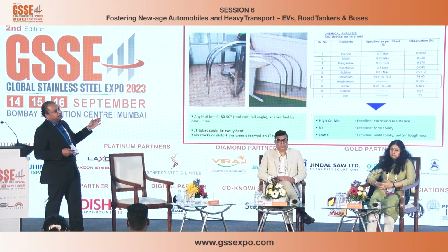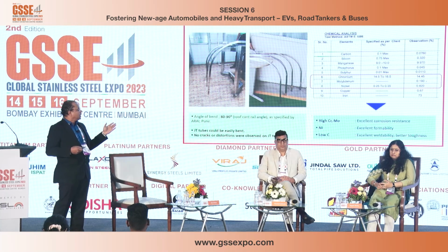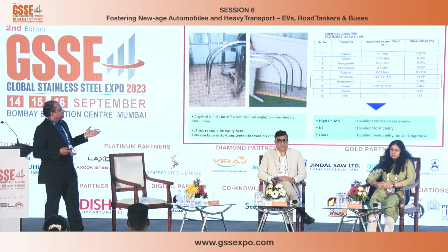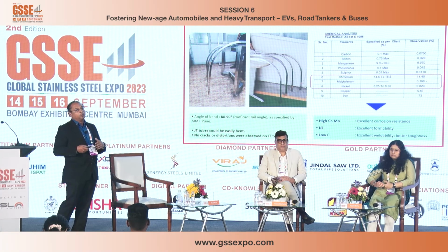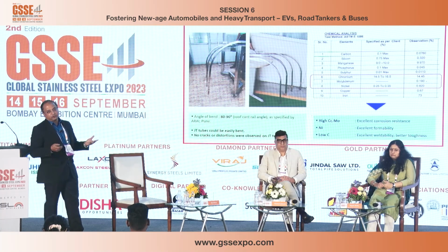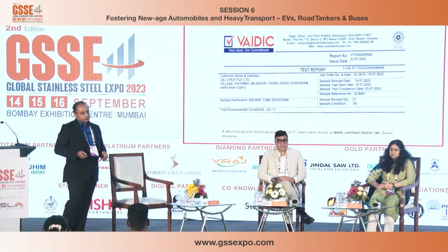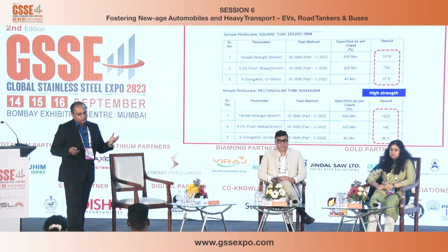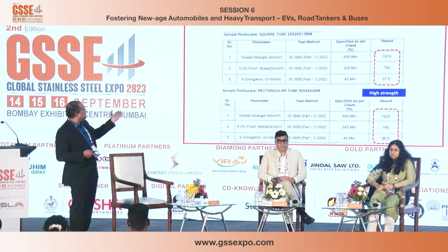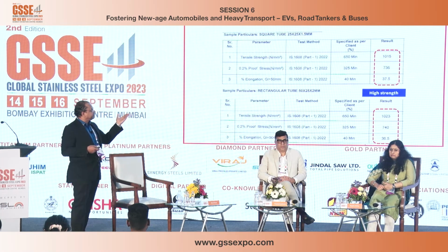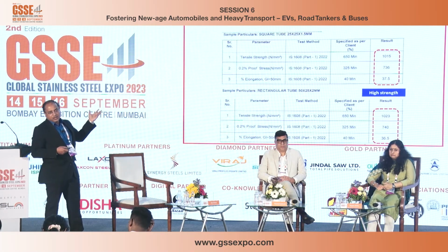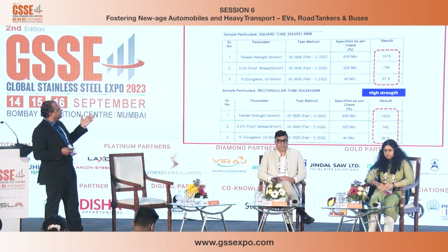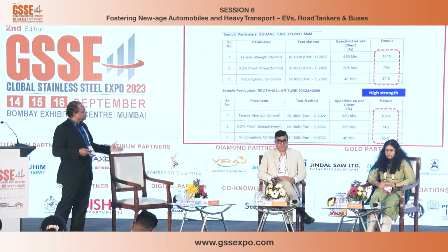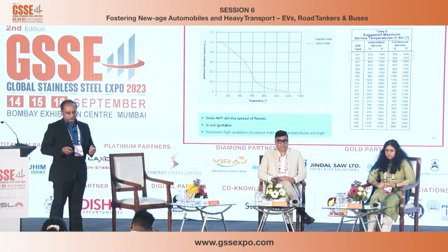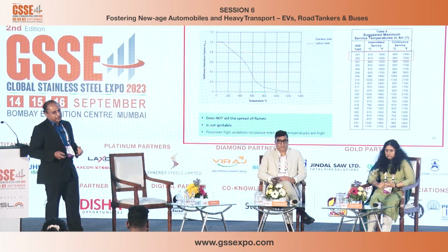And the carbon content is substantially lower. It's about 0.1%, and therefore with lower carbon, the weldability improves. In fact, the toughness also improves. So we did some tests, and as you can see, the YS is coming to about 736 megapascal for various tubular profiles. So this is 25, 25, 1.5. So you can see in all the cases, the YS is more than 700 megapascal.